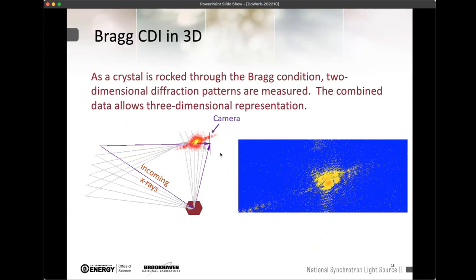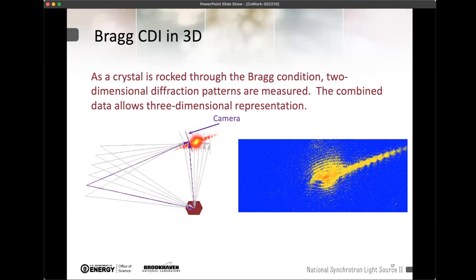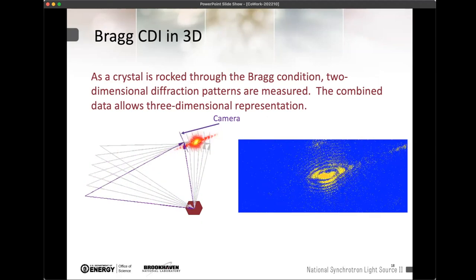In forward scattering geometry, you basically do a tomography experiment — you rock the sample around an axis and look at the patterns coming off, which has a very similar geometry to X-ray tomography or micro CT imaging. In the Bragg case, you have a non-trivial Q — the momentum transfer is not zero. You're off the (0,0,0) peak in crystallographic reciprocal space. You can rock the sample with respect to the incoming beam and take different slices, collecting the three-dimensional intensity distribution in reciprocal space. Alternatively, you can change the magnitude of the K vector by changing the energy of the incoming field, which also allows you to scan through the three dimensions.